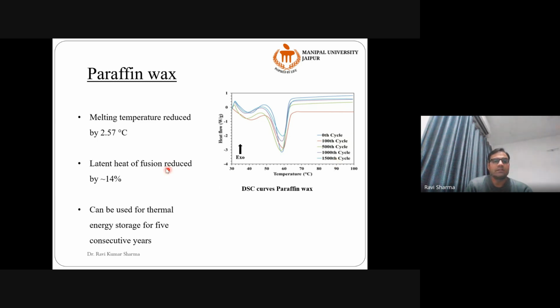So what were the results? The melting temperature changed by minus 2.57 degrees centigrade after 1500 cycles. The latent heat of fusion, which is the melting, also reduced by 14% after 1500 cycles. That means, let's say the latent heat was 100 when we bought this material, and then after 1500 times of melt-freeze, the latent heat reduced to 86 joule per gram - that's a 14% reduction.